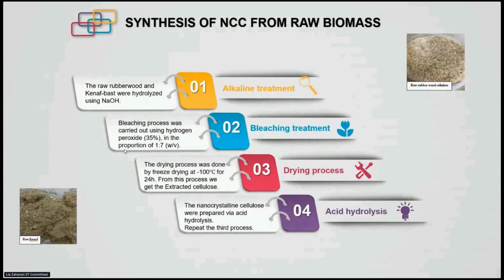Synthesis of nanocrystalline cellulose. The first step is alkaline treatment. Then we do bleaching with different parameters. We use freeze drying for our drying process and acid hydrolysis. After acid hydrolysis, we repeat step 3, the drying process.